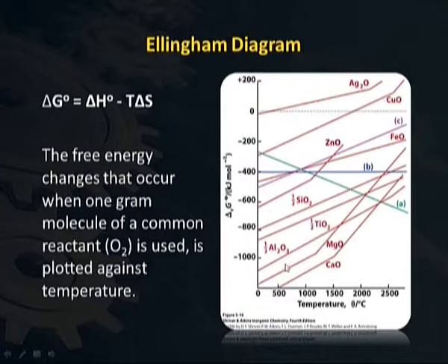So, if we have another look at the Ellingham diagram, what we are saying is, if I have zinc oxide and I have pure calcium, because calcium has a more stable oxide, its Ellingham diagram line is lower, so I can have an exchange reaction and reduce zinc from zinc oxide by reacting with calcium. Here there is a delta G naught differential, which favors such a reaction.